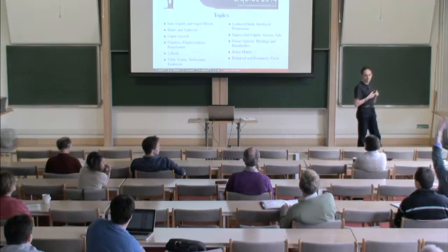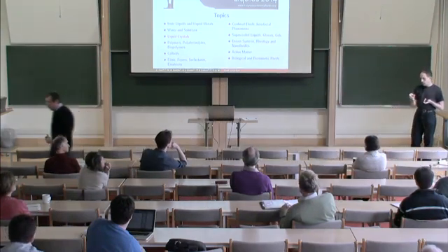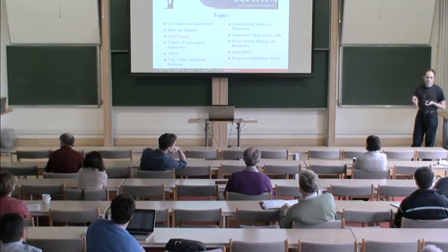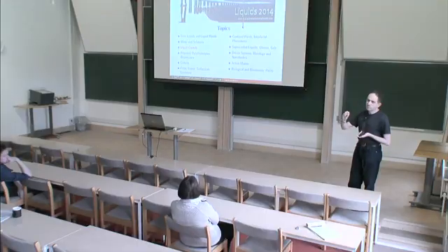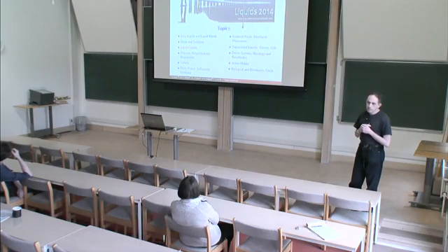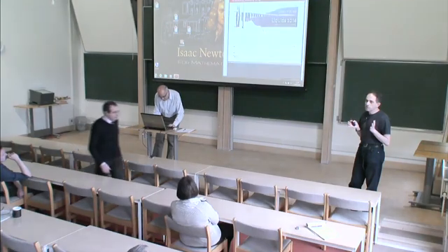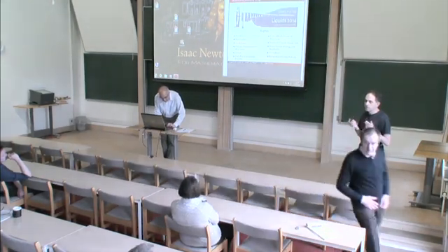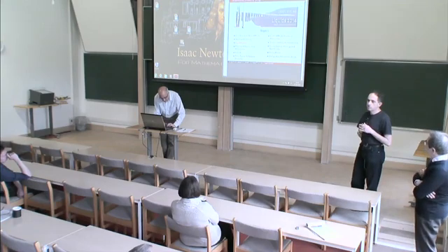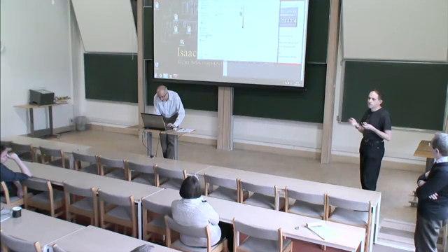Yes. The dimensions of your system? Well, the microscope slide will be on the order of a centimeter across, and the thickness is on the order of, say, 10 microns. The law you showed is for two-dimensional foams? Yes, what I showed you is von Neumann's law for 2D foams, purely two-dimensional. There is actually a huge debate over what is the correct von Neumann's law in 3D. But no, we're treating it as a 2D foam. Of course, a 2D foam is never truly 2D, but what I mean is it's a bubble monolayer.